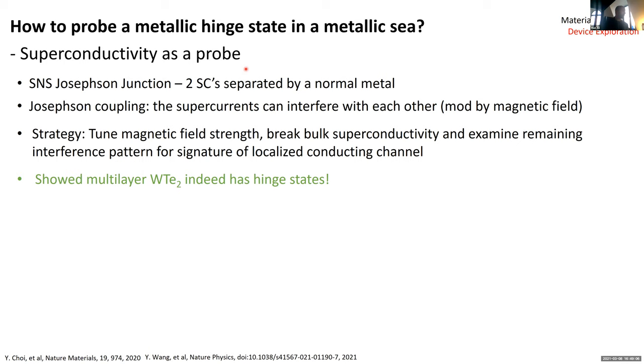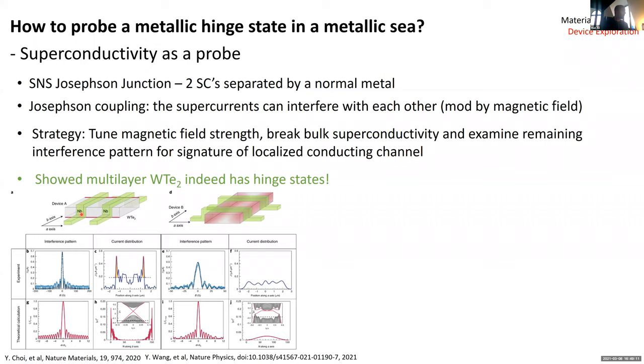We made Josephson-Junctions, which is where you take your material, tungsten ditelluride, a slab of it, and we coated niobium in two electrodes on top. And through the proximity effect, we proximatized the tungsten ditelluride into superconducting. And then we said, okay, let's look at the critical current versus applied magnetic field pattern. Now, in a normal, fully proximatized bulk superconductor, as you increase the magnetic field in this JJ, you would exhibit the so-called Fraunhofer diffraction pattern.